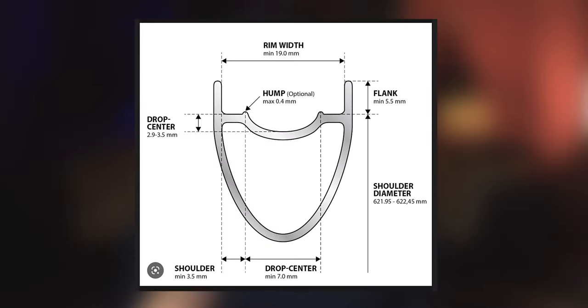What worries me about hookless is we've seen a few incidents where hookless rims have failed. Where I believe this happens is where you would have had a pinch flat on a normal clincher — instead, the tire hits the ends of the hookless channel, and because of the way carbon fiber is made, it creates a fracture and the hookless rim fails. The Zipp 303s are ones that seem to be suffering from this. So instead of getting a pinch flat, you can actually cause damage to the rim itself.